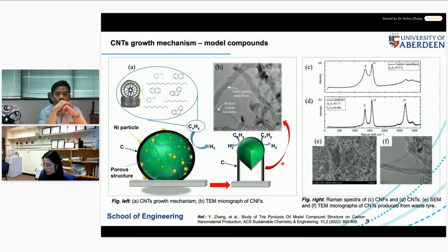And one of the challenges for commercializing this project will be the carbon nanotubes growth mechanism. Why? In general, through the thermochemical conversion process, we have to use a catalyst, and the carbon deposition on the surface of the catalyst is one of the major issues that degrade the catalyst. So researchers try to either develop a type of catalyst that is resistant to carbon formation, or the other way is to understand how this carbon was formed on the catalyst, and meanwhile convert this problematic carbon into high value carbon nanotubes. That was my aim. So I would try to investigate the synthetic growth mechanism from this process and to see how these carbon nanotubes form.